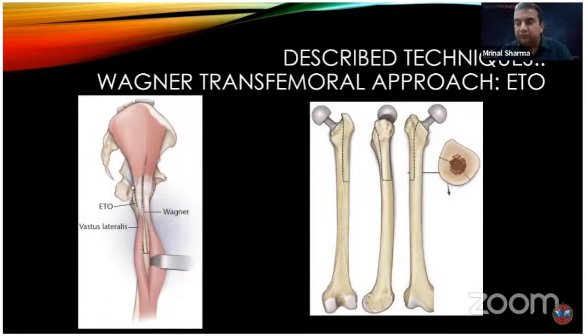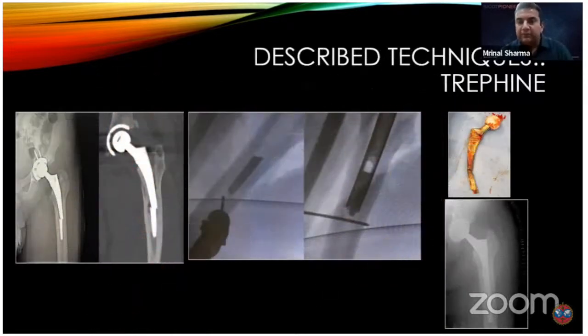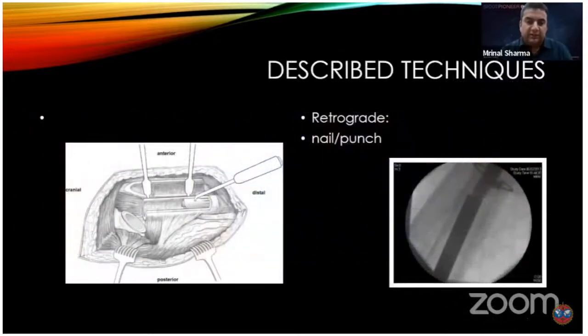The described techniques to revise these stems: the commonest one, which Dr. Manzary has already described, is ETO, which I'll be using in my case report as well. Other described techniques use trephine burrs, where you use a trephine like a hollow mill. You can see the K-wire, which prevents the distal tip of the stem from migrating, and then it has been revised with a tapered fitting distal stem. Another technique where a stem has broken uses an ETO, and then with a carbide burr, you make an indentation into the distal part of the stem in the proximal part of the broken fragment. And then you hammer it out, probably loosening it around with a pencil tip burr.